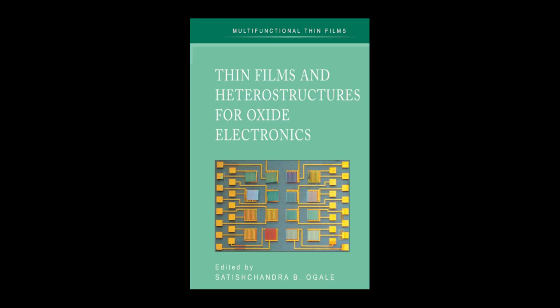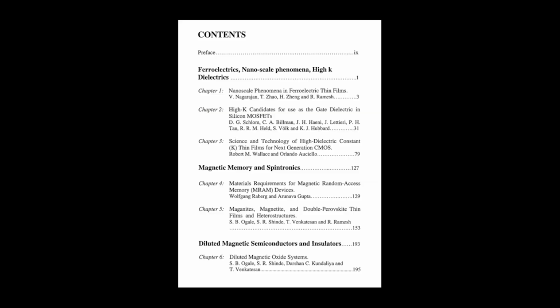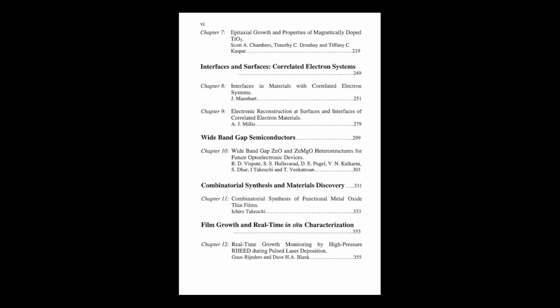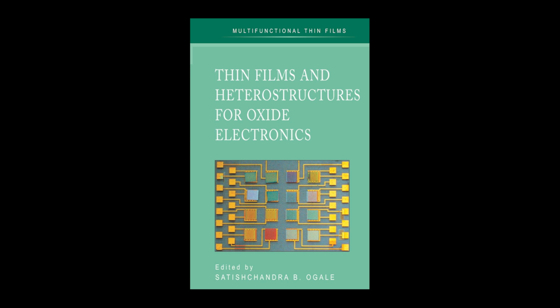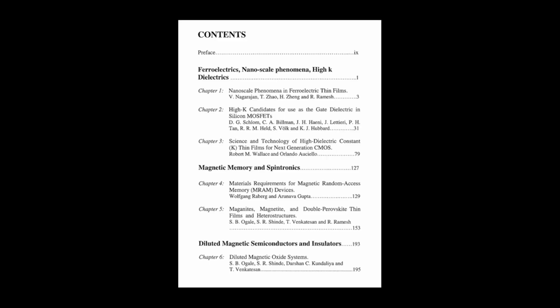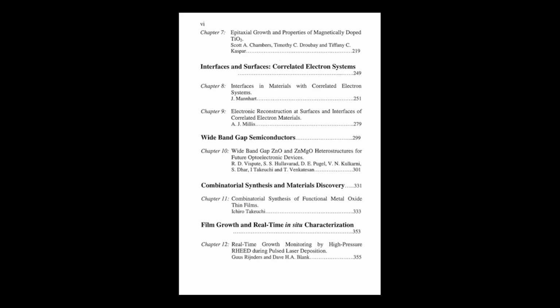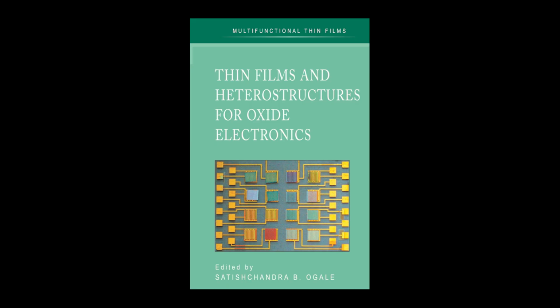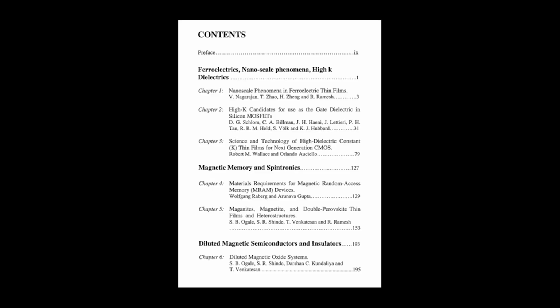So, what was the early evidence that made people think it was intrinsic? Well, initially, there were some pretty compelling signs. Structural studies, like X-ray diffraction, often suggested that the cobalt atoms were indeed sitting on titanium sites in the anatase lattice. Okay, substitutional doping seemed plausible. And there was a charge balance argument, too. Cobalt usually goes in as Co2+, but titanium is Ti4+. To make up for that charge difference, the material tended to form oxygen vacancies. Missing oxygen atoms. Right. And these oxygen vacancies can act as shallow donors, providing electrons. So people proposed a formula like Co_xTi_(1-x)O_(2-δ), suggesting the Co substitutes, vacancies form, and maybe these extra electrons help mediate the magnetic interaction between the Co ions, some kind of carrier-mediated ferromagnetism. So the vacancies played a necessary electrical role, providing the carriers needed for magnetism.